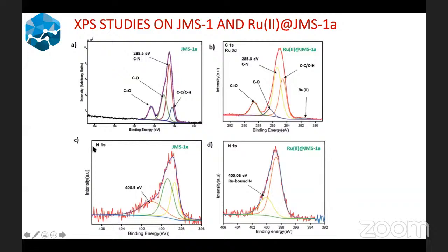We also expected the binding energy to decrease upon coordination of the ruthenium to nitrogen. And as you can see here, we have 400.9 in the as-made MOF, before functionalization. And upon insertion of the ruthenium complex, the binding energy shifted to 400.06 electron volts, which confirms successful grafting of the ruthenium p-cymene complex into our MOF.